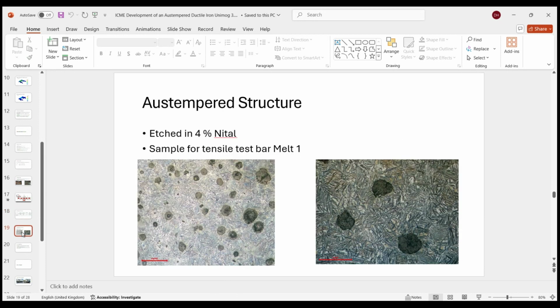And here we can see the microstructure we achieved for the ADI 900. This is a typical structure for an ADI 900, an ausferrite structure. Contains ferrite platelets and high carbon stabilized austenite. The austenite volume would be around 35 to 40% for this grade of ADI.